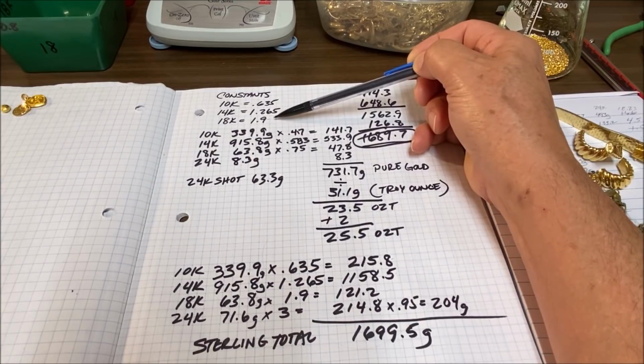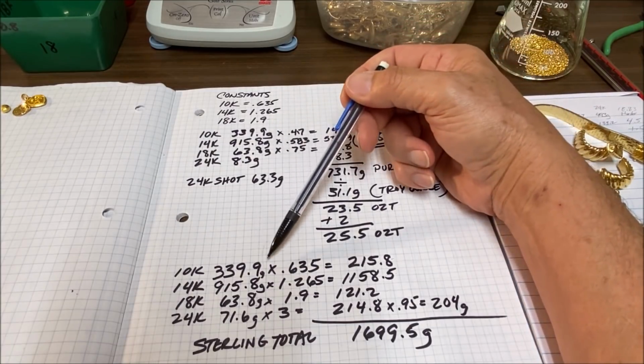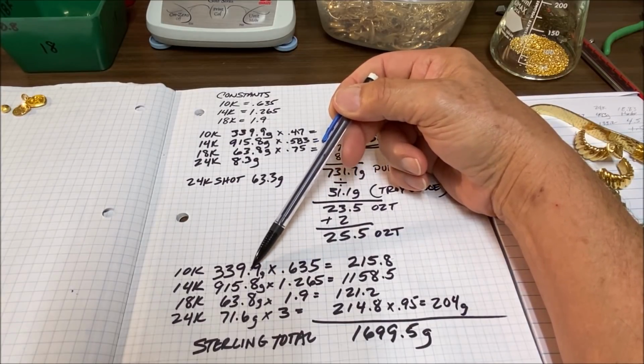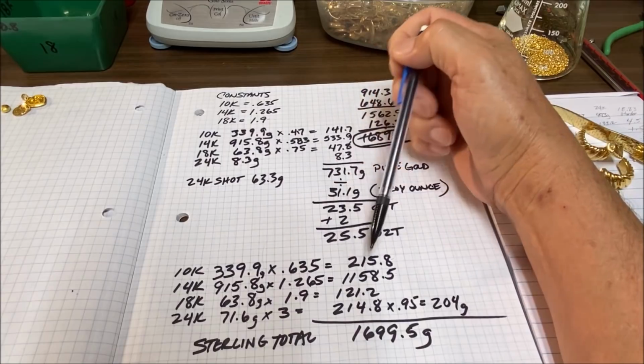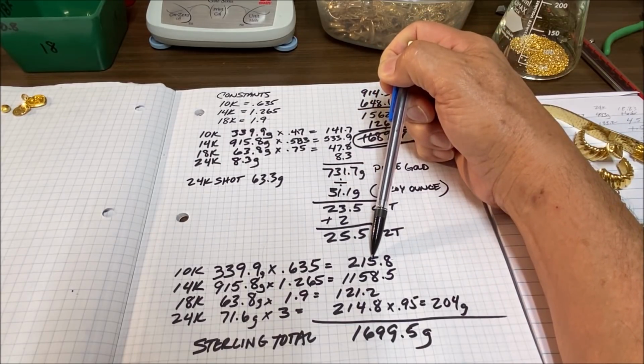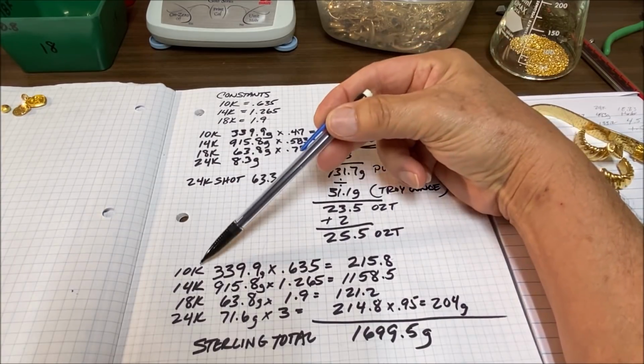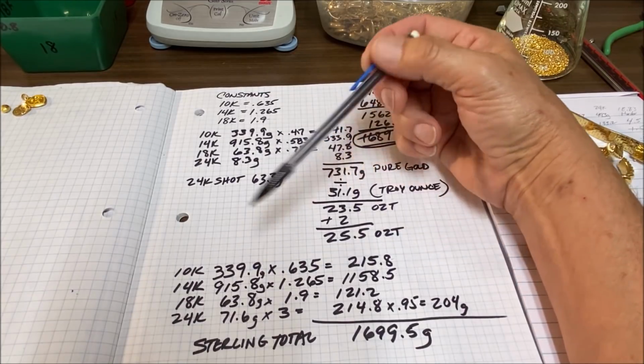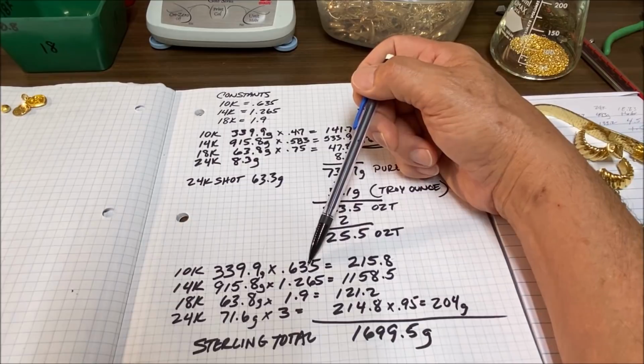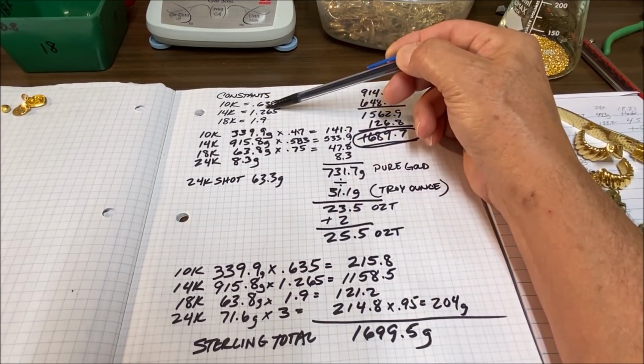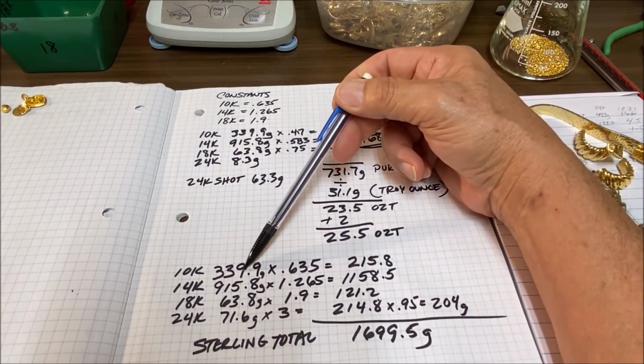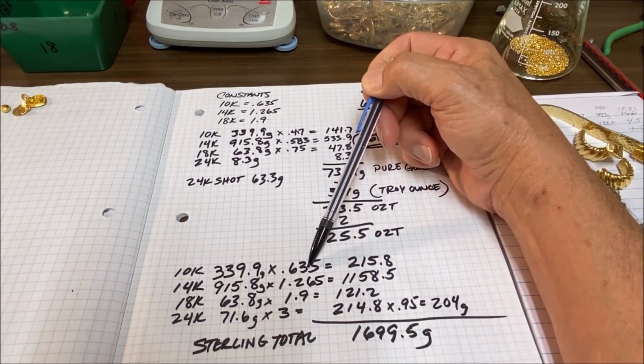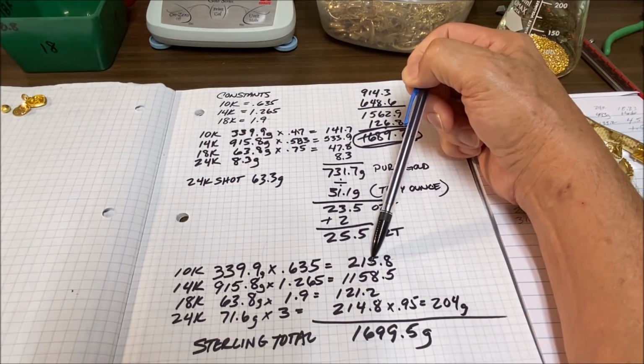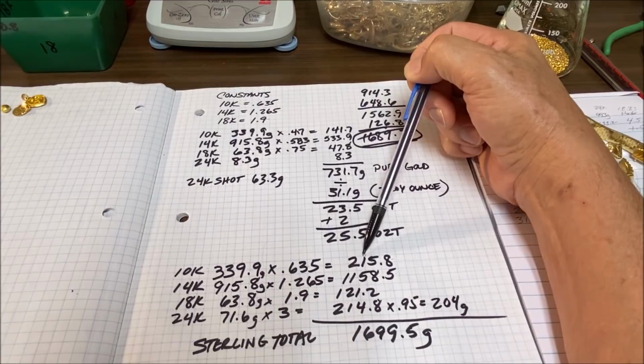These are the numbers that I use to multiply by the number of grams of 10K to get the amount of sterling silver that I need to add to get a proper inquartation. 10K gold, I got 339.9 grams. I multiply that by this constant right here, 10K. Up here, see it says 10K, 0.635. I multiply the number of grams of 10K I have by 0.635, and that tells me I need 215.8 grams of sterling silver or copper, whichever your case may be.